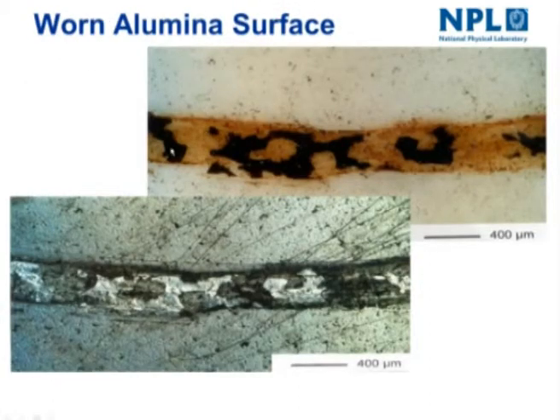So an example of just optical microscopy is these two micrographs. This shows what's called the bright field micrograph, and this is an alumina surface, by the way, and this is a transfer layer on the surface. This was rubbed with steel, by the way, and you think the steel has transferred to the surface. We use cross polars here, and this is on most optical microscopes, to show that in actual fact what you think is the steel transferred to the surface is actually iron oxide, and you can now see the brown color that's been revealed. And if you get the conditions right, you can see that this is a dark shade of brown, as it were, as well. So this is definitely iron oxide, and you've identified that very simply from optical microscopy.